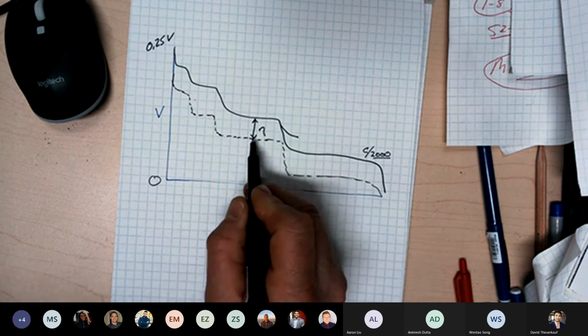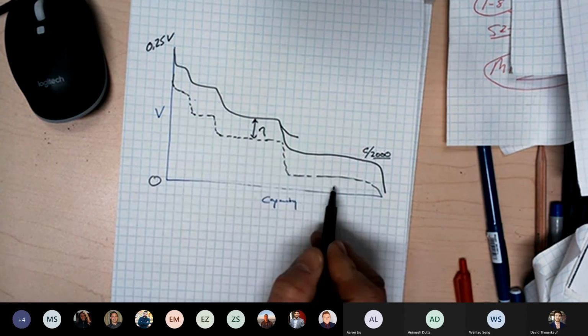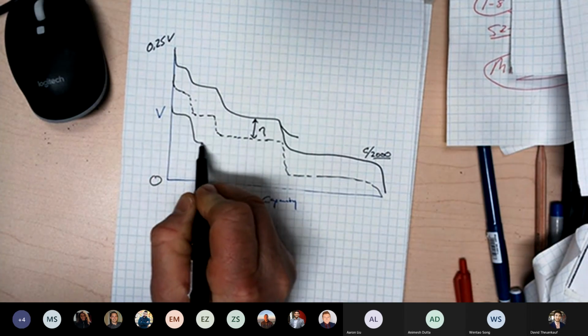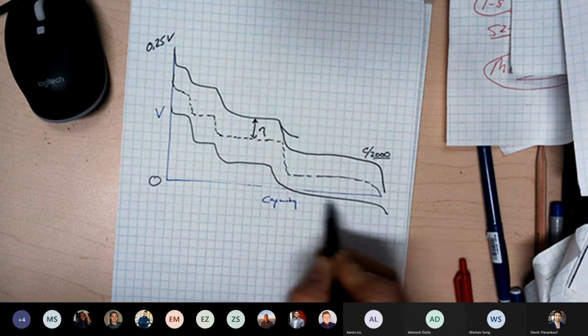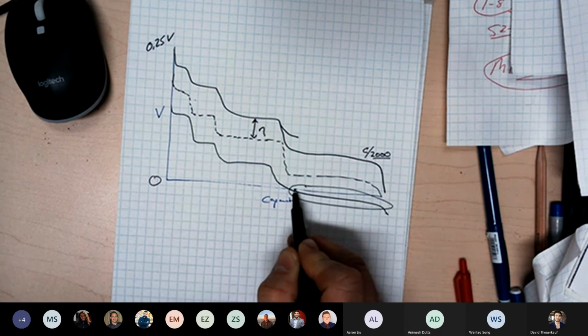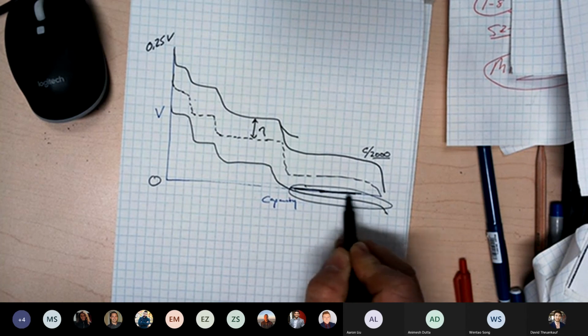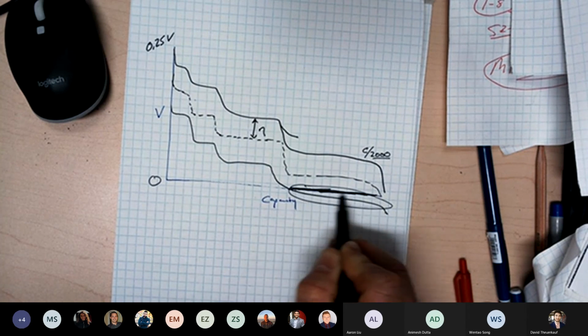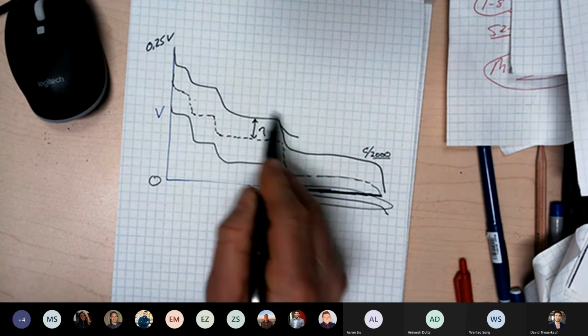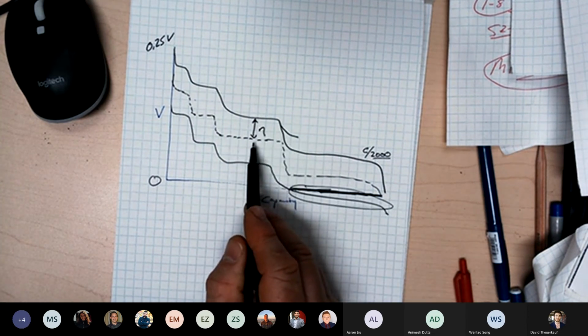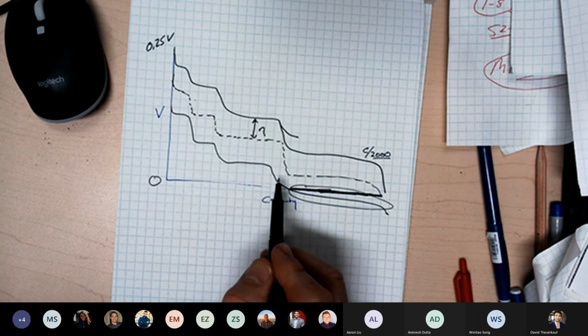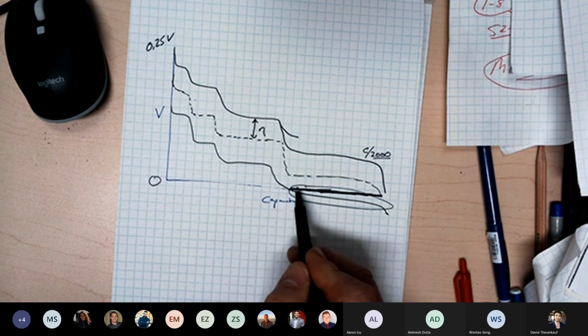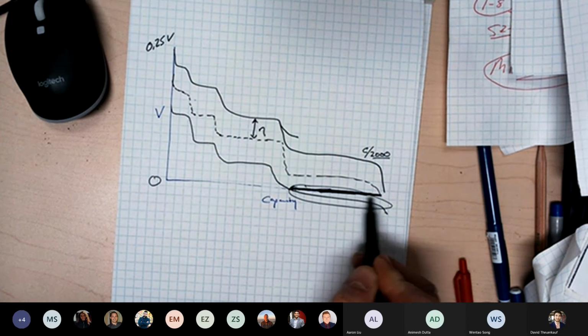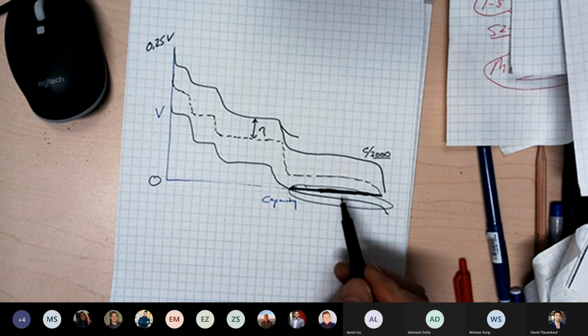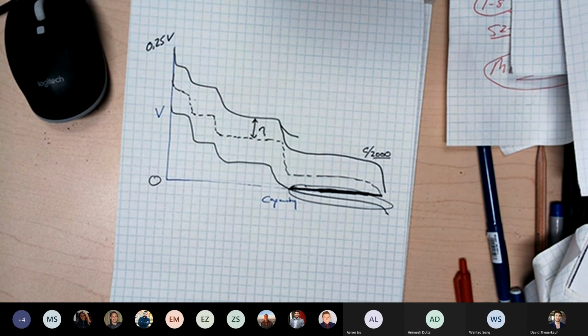But the issue is, if this lithiation rate becomes too large, this shifts down even more, and part of the curve goes below 0. And when that happens, the lithium would rather electroplate on the surface at 0 volts. Okay, so the portion of the overvoltage due to the electrolyte is what you want to minimize. And you can do that by improving the conductivity of the electrolyte and the lithium diffusion constant in the electrolyte. And we're going to talk about all those things in the next few lectures. So hopefully that answered your question a little bit about what is overvoltage.